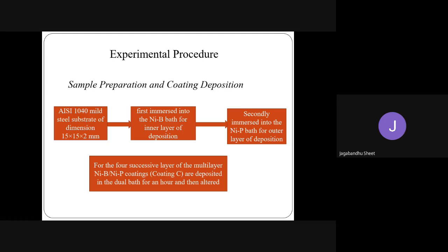The temperature range is 90 plus or minus 2 degrees centigrade. This bath is used for the NIP as the outer layer, and when NIP is the inner layer, this bath is used for the first bath, and NIP as the second bath. For the four successive layers of the multi-layer NIB by NIP coatings, the coatings category C are deposited in the dual bath for an hour.